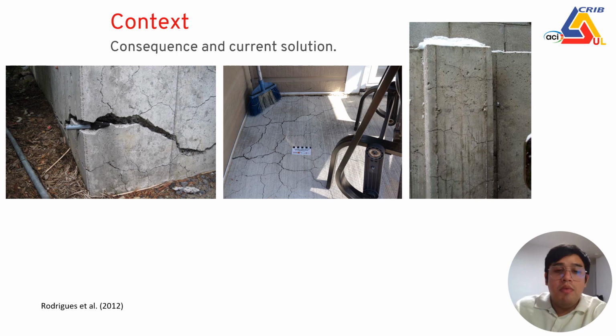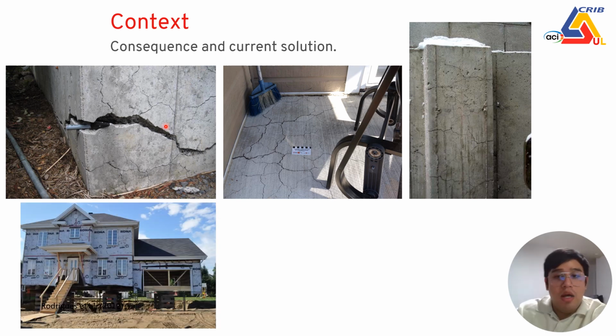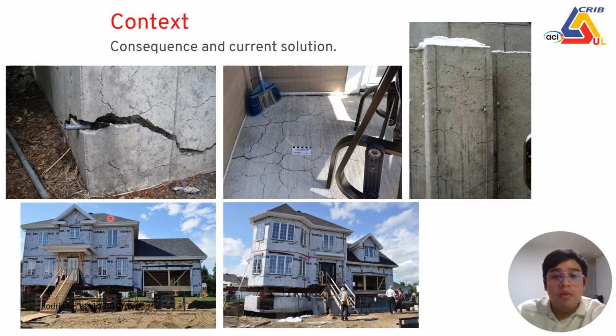Both reactions mentioned before will create secondary products that are really expansive. So they will start creating micro cracking in the cement paste until it reaches the surface, as we can see here, in a really bigger map cracking effect. So for this problem, there was not an easy solution, and the only solution that they could think of was to lift the houses, and the people were living elsewhere for around 2 months, and after that they reconstructed the foundation and then placed the house again on the site.